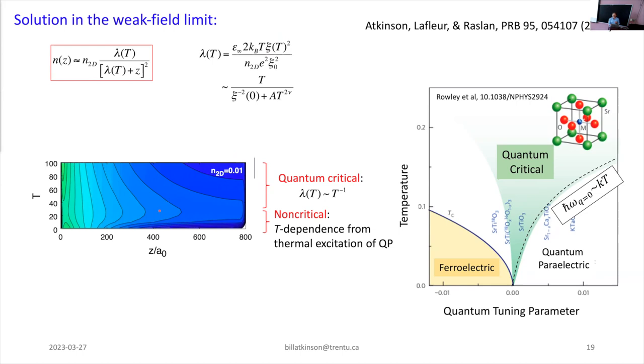And this explains the temperature dependence you see here. So initially, it's the numerator that wins and the length scale grows. And then at high temperature, the denominator kicks in and the length scale shrinks. So the temperature factor in the numerator is coming from the Fermi-Dirac distribution for the electrons. So it's just the electrons spreading out. And then the temperature dependence of the dielectric function is coming in the denominator.